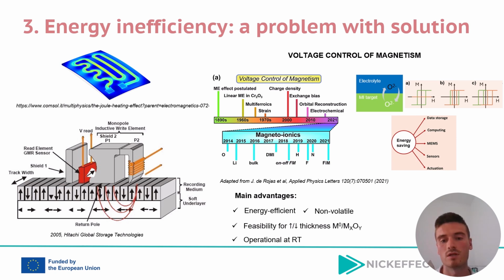The progression includes interesting concepts like strain, multiferroics, charge density, or electrochemical magnetoelectric control mechanisms. Among different approaches included therein, Magneto-ionics involves controlling magnetism via voltage-driven ionic motion. This method shows potential to significantly reduce Joule heating by eliminating the need for current-driven magnetic switching. The timeline below the chart highlights key developments in Magneto-ionics across various ions and mechanisms, such as oxygen, lithium, hydrogen, and nitrogen, among other light elements, and their effects on ferromagnetic, antiferromagnetic, or ferrimagnetic states.